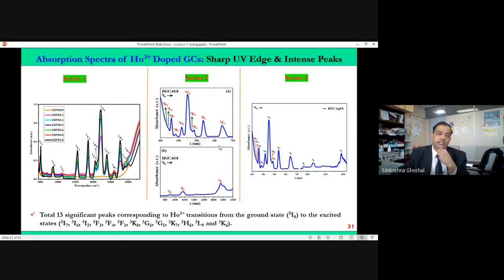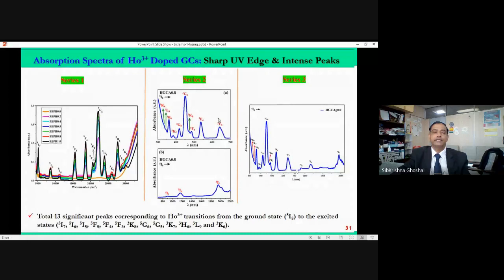Then we look at the structural symmetry. After looking at the structural dielectric correlation, then we go for the optical studies. Because remember, the main aim is to do the optical properties, but optical properties depend on the structural symmetry. So first we look at the absorption in all three series, and we see that as we are doping the nanoparticles in the system together with the rare earth, the absorption is becoming cleaner and really getting high. And some of the new absorption peaks, which were weaker without nanoparticle, become stronger with nanoparticle. So we are therefore on the right track.